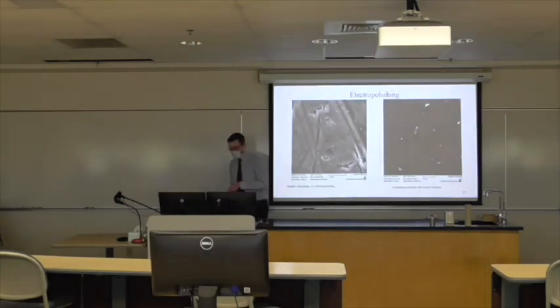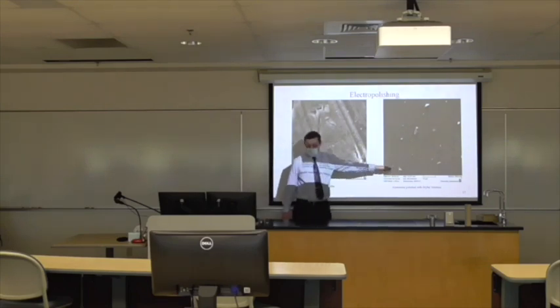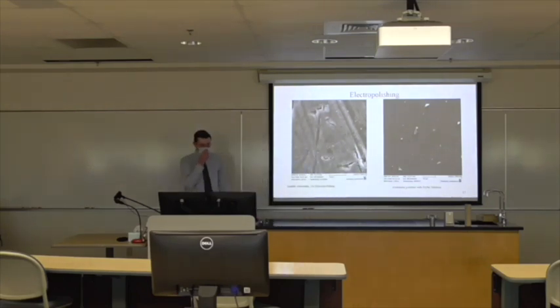When we did the Brytal electropolishing, it works very well. On the left side here is just a sanded piece of aluminum that was already annealed, and as you can see, it has defects at the micrometer level. When it's electropolished using the Brytal solution, it has some defects still, but is very well polished. This result we could not reproduce because of this same issue with the open beaker system. So the Brytal electropolishing method works well, but there are challenges, especially having it work without a special apparatus.